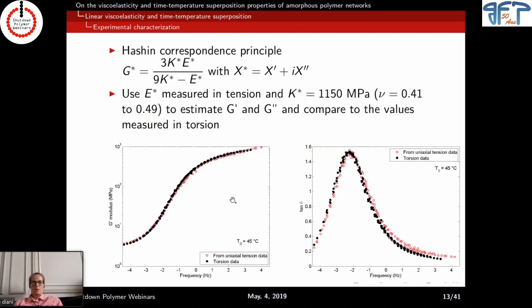Okay. So doing that, we can use the value of E star that we measured. We need to make an assumption for the bulk modulus because there are very few apparatus that give you access to the viscoelasticity of the bulk modulus. And we thought, okay, we're going to assume it as elastic because, okay, it changes over temperature, so it's viscoelastic, but the order of magnitude is 2, 3, when Young modulus or shear modulus are changing by 3 orders of magnitude. So we're going to assume it constant and calculate G prime and G double prime with a measured value obtained in uniaxial tension and compare it to the G prime and G double prime measured during the torsion test. When we do that, we can see that we have very nice superposition.